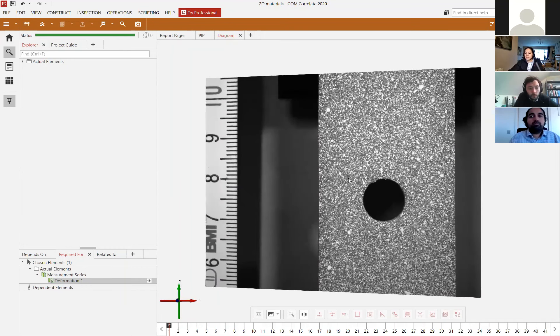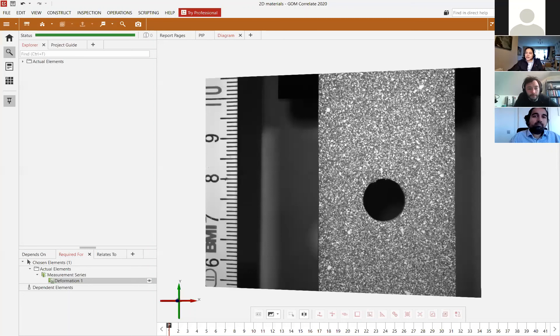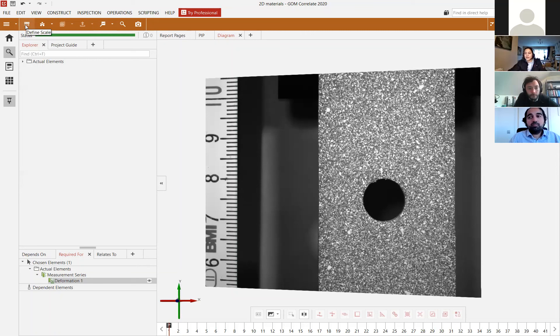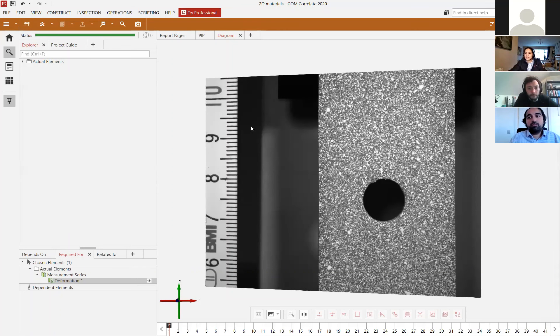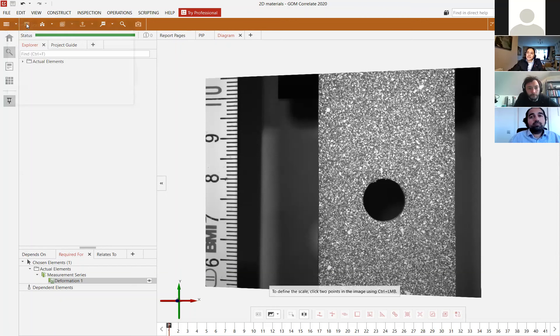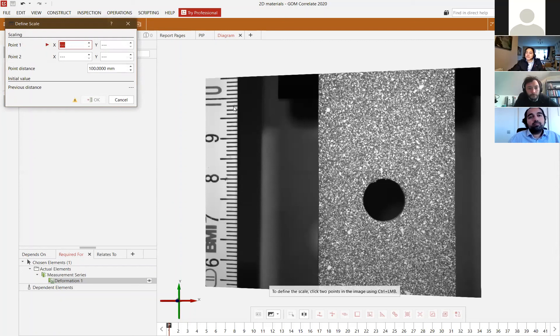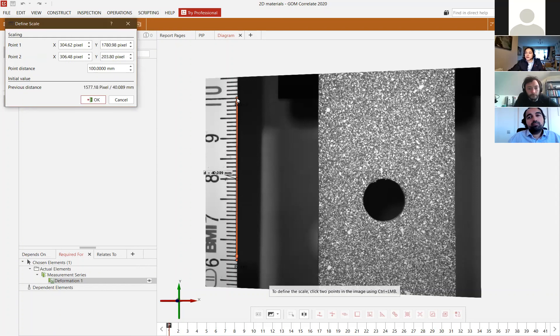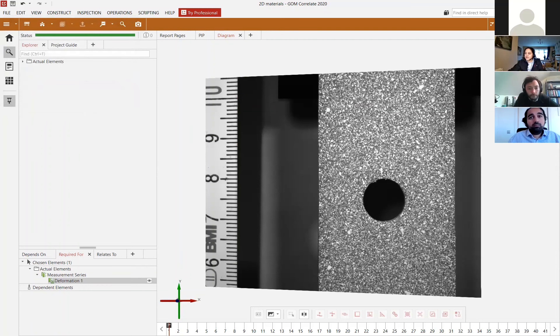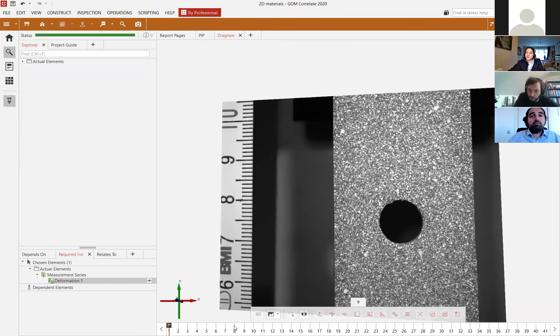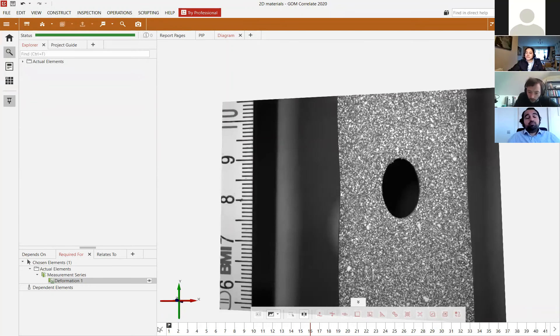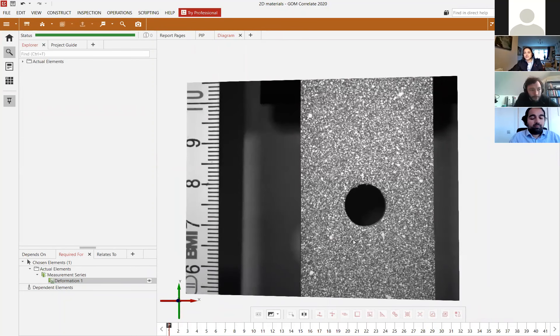Okay. So this is a brand new project. I've not done any analysis on it. All I've done is we've got the images. So within the GOM software, we're just going to work left to right through this colored toolbar until we've got the results that we want. So first, we need to define the scale. The software doesn't know how big each of these pixels are because we've just imported the images. So it doesn't know if this is 2 millimeters large or 40 or 400. So let's define a scale. And we've got this ruler, which of course has to be in the same plane as the sample to help us define the scale. If you know the thickness of your sample or the width of your sample, you can use that as well. So I'm going to click on two points, apply 40 millimeters between the two points, and now the software knows the scale of the images and will assume the same scale. It is possible to scale each image individually, but that's not going to give you the most accurate results.